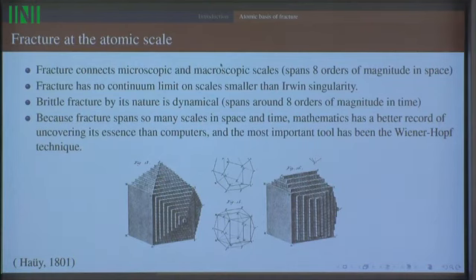So here are some of the essential points. Fracture is a process that connects microscopic and macroscopic scales. If you take a centimeter scale sample and you break it, then you're connecting 8 orders of magnitude in space. There is no continuum limit that can describe the process once you go down below the level of the standard continuum theory, which I will call the Irwin theory.